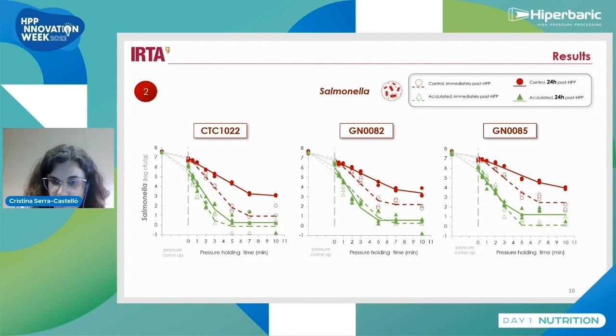What does it mean? It means that during these 24 hours at 4 degrees, Salmonella was able to recover some viability, and for this we obtained lower inactivation. However, this was not a clear case for the acidulated samples, the ones to which lactic acid was added. Here you can see that for the samples enumerated 24 hours post high pressure processing that were acidulated, no statistical difference was observed compared to those obtained immediately post high pressure processing.